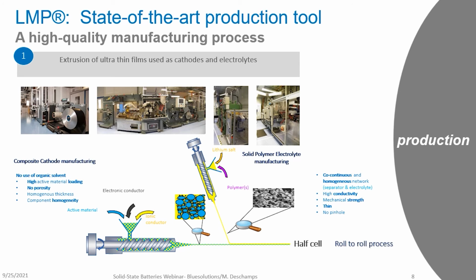To make this separator, we are using two different polymers, one for ionic conductivity and the other one for mechanical strength. We need to make a co-continuous and homogeneous network, the thinnest possible, but with no pinhole and with homogeneous thickness. At the end, we have made what we call a half cell.